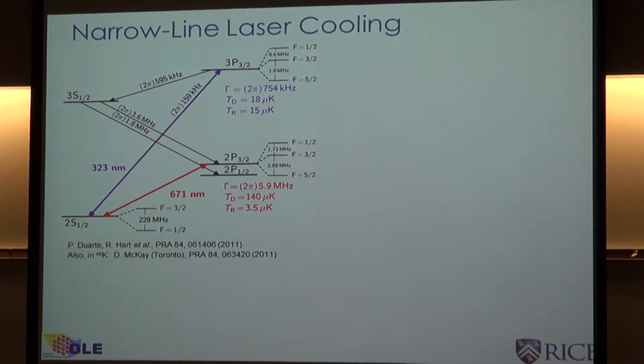All right, so I'm going to digress just a little bit because this is kind of cool. Lithium has been difficult to laser cool through the years because we can't do sub-Doppler cooling. I know there are a lot of experts in the audience who use rubidium, and you get to very low temperatures in rubidium just in a Mott. We can't do that, and we've been envious of that for many years. This is the usual transition that we use, and because of unresolved hyperfine structure in the excited state, we can only get to the Doppler temperature of 100 to 200 microkelvin. But if you use a more narrow transition, the 2s to 3p in the UV, it's about a factor of 7 narrower, and because of that the Doppler limit is a little bit colder. So it potentially is a better starting point.